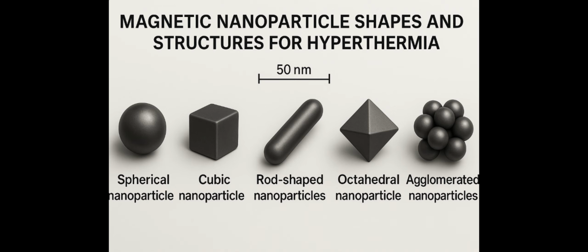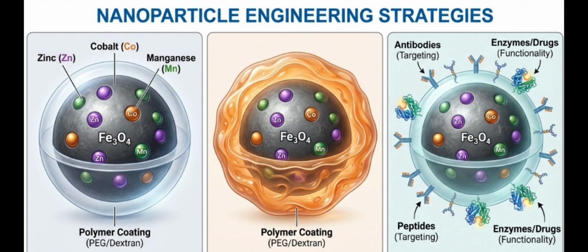The multi-core or nanoflower structure, in which many magnetic cores group together inside a single particle, is another effective design. Under therapeutically safe magnetic field intensities, their linked magnetic moments improve specific absorption rate and increase magnetization, enabling effective hyperthermia. Another effective engineering tactic is doping. Researchers can adjust the crystal lattice and alter magnetic anisotropy, coercivity, and saturation magnetization by partially replacing iron with metals like manganese, zinc, or cobalt. For instance, under clinically safe fields, cobalt-doped ferrites typically show stronger magnetic responses.